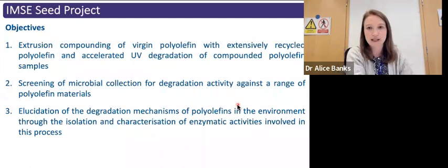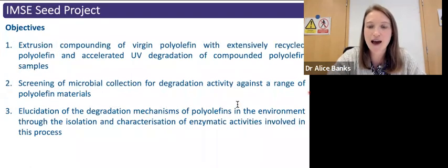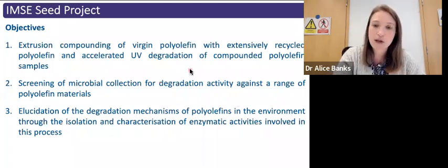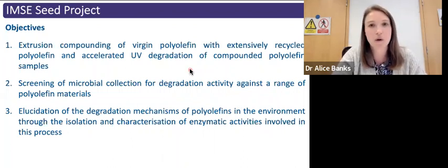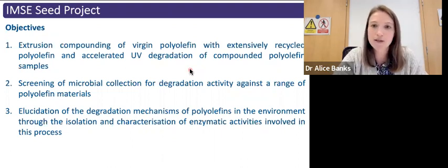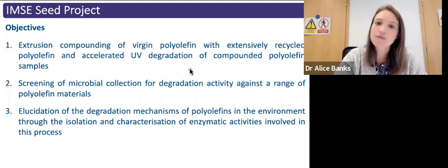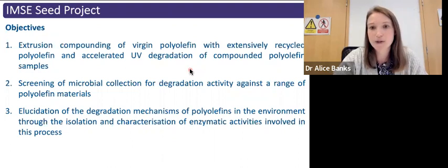So we have three main objectives to carry out, and the first of these is to produce a range of different polyolefin materials, both polyethylene and polypropylene, that will be manufactured with a range of different compositions and properties. So this is going to include materials manufactured to include recycled content in line with the UK Plastics Pact. Also materials exposed to harsh weathering and pre-treatment conditions, and then samples which contain technology which has been developed by Polymateria to aid biodegradation.